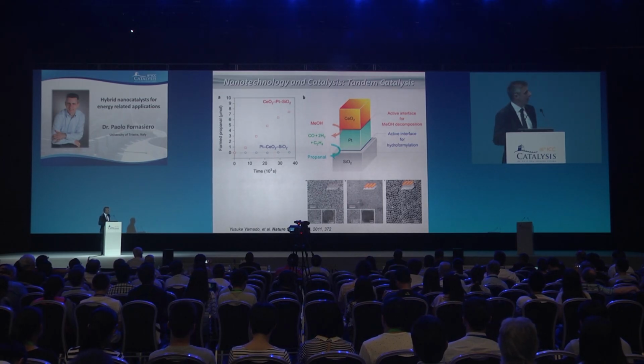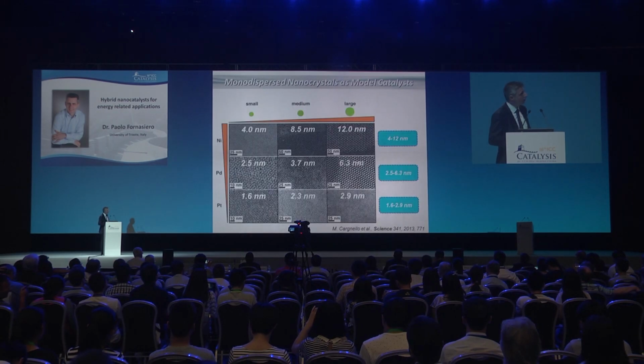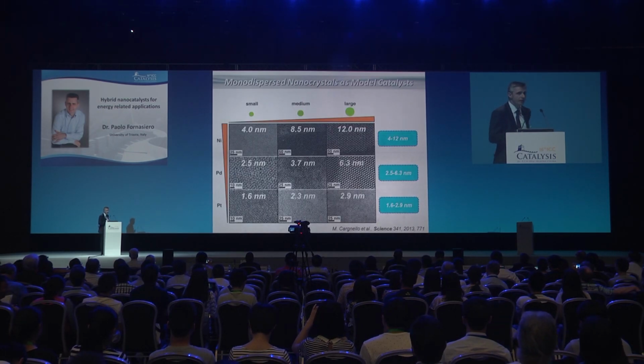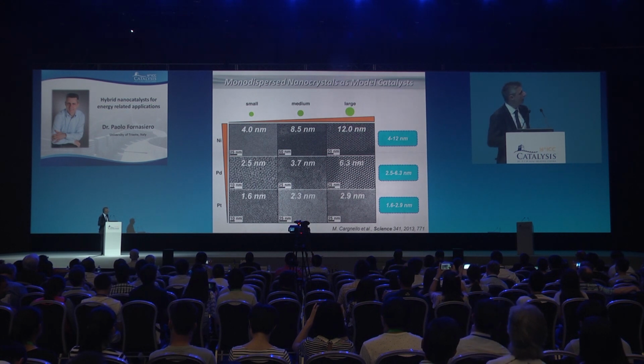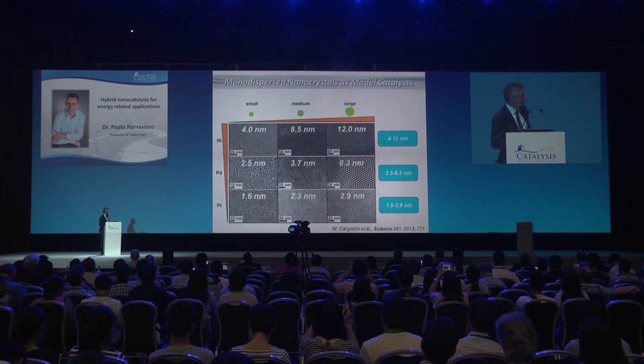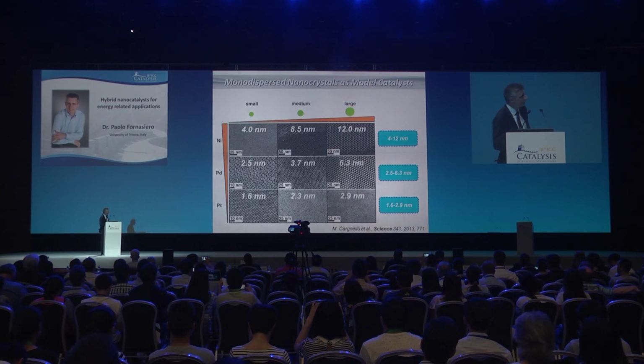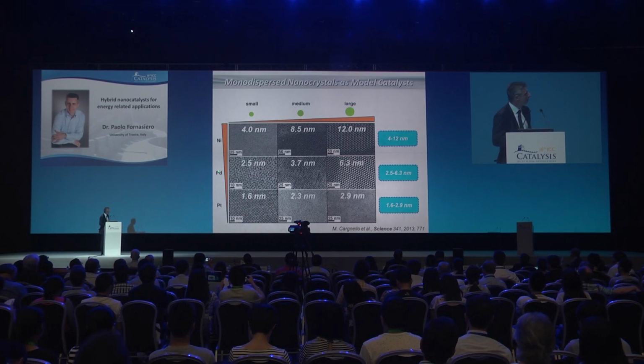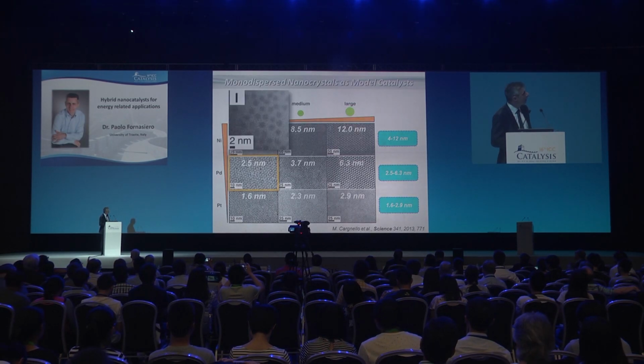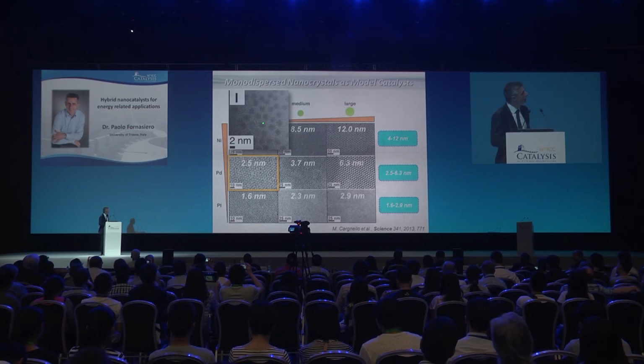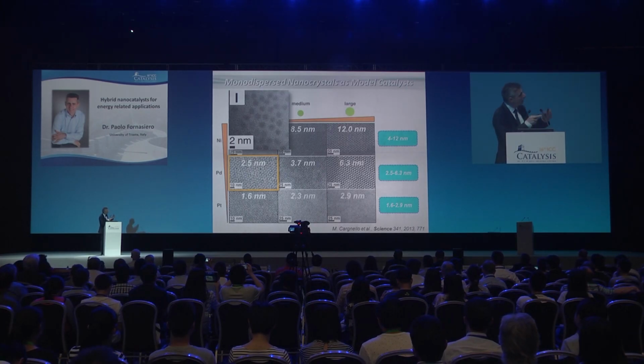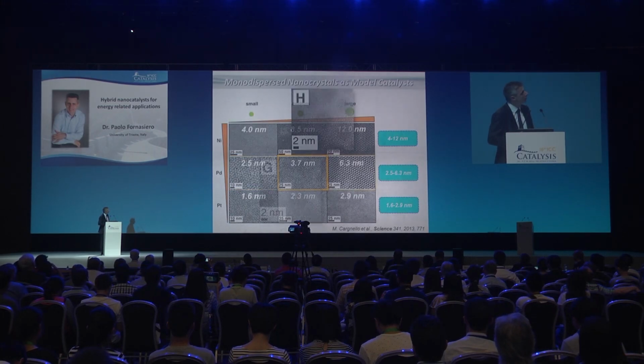So we have done a lot of work also in the area to understand the role of the metal-support interface, and in particular we have prepared monodispersed nanocrystals of different catalytically active metals like nickel, palladium, and platinum, obtaining, let's say, small, medium, or large particles depending on the reaction conditions. These nanocrystals are all equal in size, and the difference might be just one atomic layer, so they are really monodispersed.